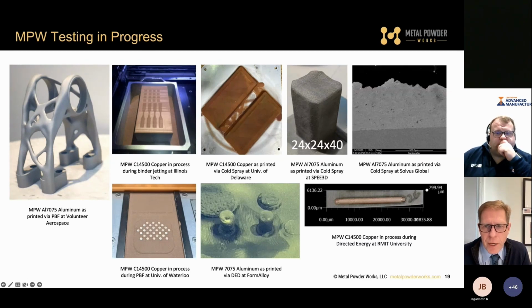We've done some cold spray work of both copper and aluminum, and you can see the adhesion interface that we get. So we're working to dial this in. We're now giving the cold spray people more degrees of freedom. We can tailor the hardness of the powder through the heat treatment, and that controls the deformation behavior. We've also done some DED work with the Formalloy process, showing preliminary results that the powder moves through the process fine. We've got some copper work done at RMIT University on a Trumpf system. We're getting ready to do some work with NASA on an RPMI system in concert with Elementum 3D.